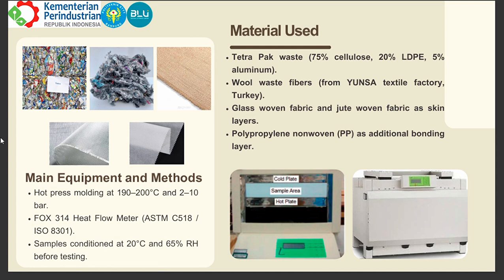Each component was chosen for its recyclability, thermal behavior, and compatibility in composite manufacturing. The main equipment and methods they are using is hot press molding machines that operated at 190 until 200 degrees Celsius and 2 until 10 bar pressure to fabricate the composite sheets. They are using the FOX314 heat flow meter used to measure thermal conductivity, resistance, and related properties. Before testing, all samples were conditioned at 20 degrees Celsius and 65% relative humidity to ensure uniform moisture content and accurate results.